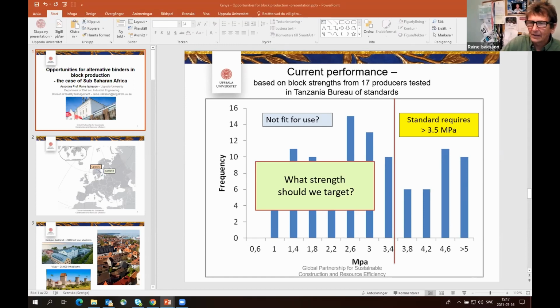But does it mean that they are not fit for use? Are people stupid when they buy them and build their houses? It might be turning out that what is stupid is the standard, which probably is inherited from a British standard somewhere, which comes from different conditions and maybe randomly has put the compressive strength requirement at 4 megapascals. Because if you think of it, 4 megapascals for a 6-inch block means that it can sustain 24 tons, a reasonably big lorry. Now, when you build a single house with a tin roof, you don't need 24 tons.